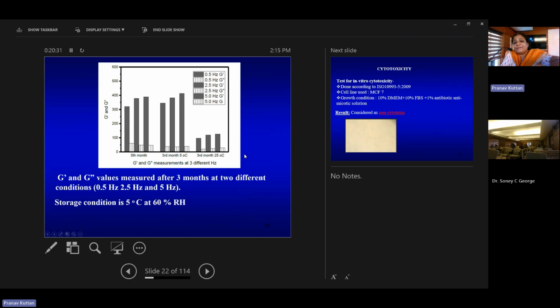That is the first: at different frequencies, we checked the rheological parameters at the 0th month and 3rd month, at two different temperatures, 5 degrees Celsius and 25 degrees Celsius. It was found that when we stored the product at 5 degrees Celsius for 3 months, there was no change in the rheological parameters. But the product kept at 25 degrees Celsius showed a reduction in all the modulus. So that was not considered, and we optimized the shelf life, that is the storage condition, accordingly. That is, 5 degrees Celsius is the storage condition for that particular type of product.